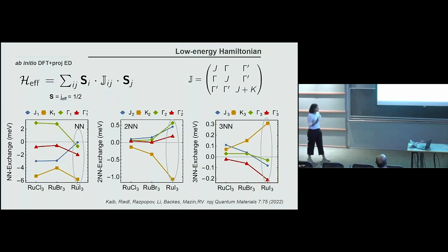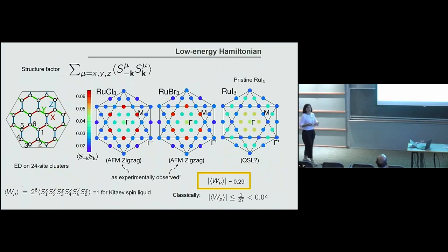So this defines a slightly different type of model for this ruthenium iodide. We analyzed the ground state of this model by doing exact diagonalization on 24-site clusters. With these models that we obtain with a minimal set of parameters, up to 5 parameters, for ruthenium chloride the ground state is the zigzag order. For ruthenium bromide, the ground state is the zigzag order, as you can see here in the Q vectors. However, for the ruthenium iodide, we don't find a long-range order.